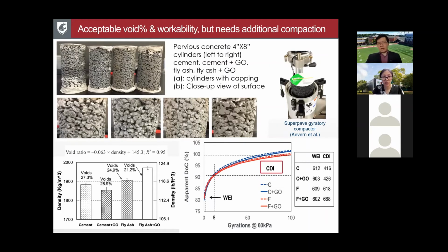And again, the bottom right, we're dealing with compactability. This is a test derived from Superpave gyratory compactors. So there are indices which include the WEI and CDI. The WEI basically is an indicator of workability. As you can see, all four groups share similar workability. And CDI, however, indicates the amount of energy you need to compact the pervious concrete. And you can see the fly ash ones do require significantly more energy to compact them. The presence of GO further increased that amount of energy a little bit, but still they're reasonable,